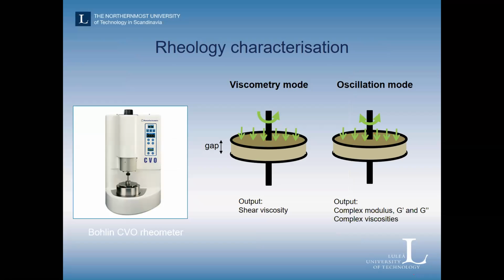Rheology characterization is an important thing to characterize when looking into the processability of this type of resin. For that purpose, we've been using a rheometer both in viscometry mode, where there's a continuous rotation, continuous shearing of the viscous fluid, and in an oscillation mode, where we detect the complex modulus and complex viscosity, and sort of both the elastic and viscous part of the response.